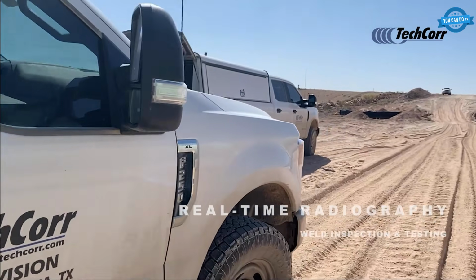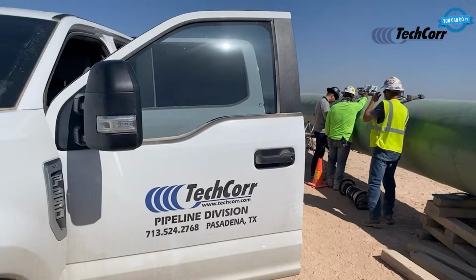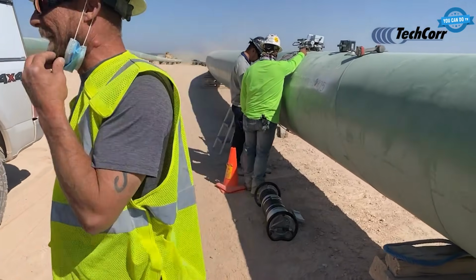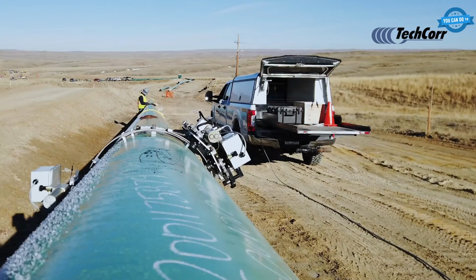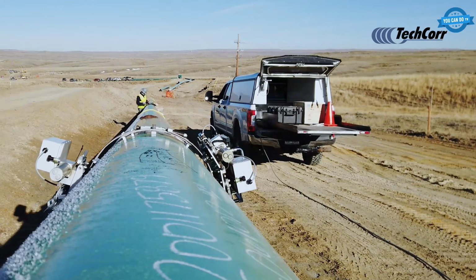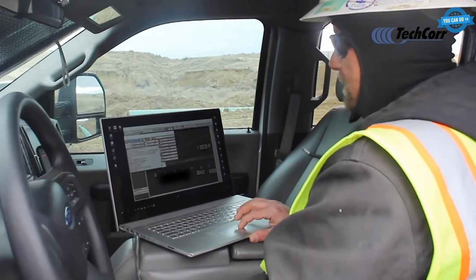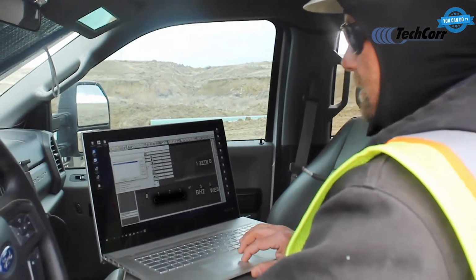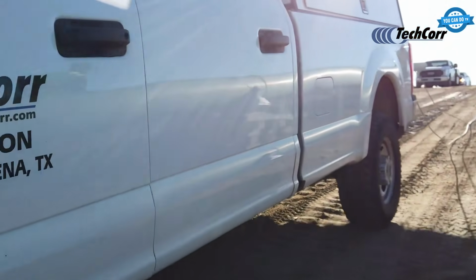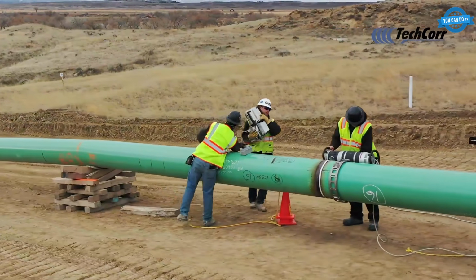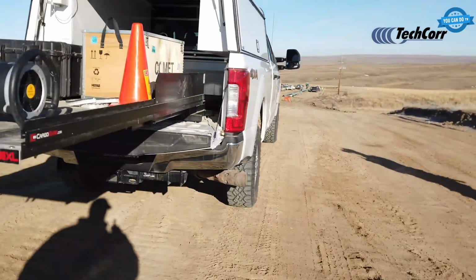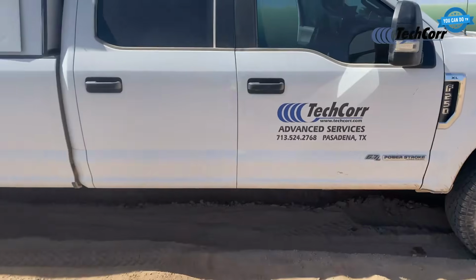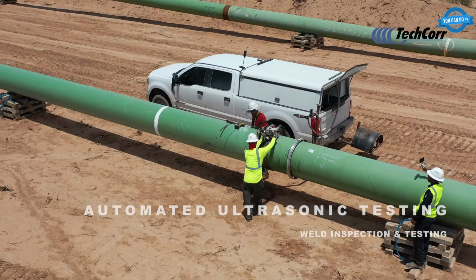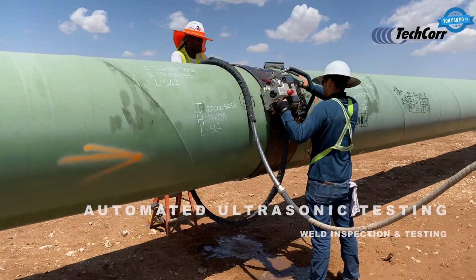A radiographic crawler is sent through the inside of the pipe to the position of each new joint. From the outside, a corresponding detector captures the image. The internal structure of the weld appears on a screen within seconds. Inspectors look for cracks, lack of fusion, porosity, and inclusions that cannot be seen from the surface.